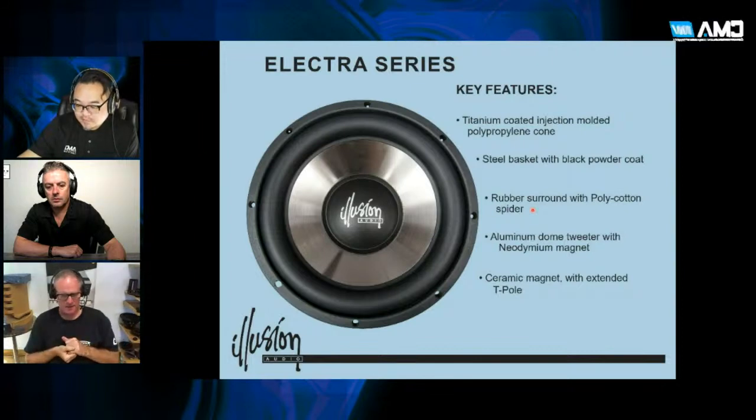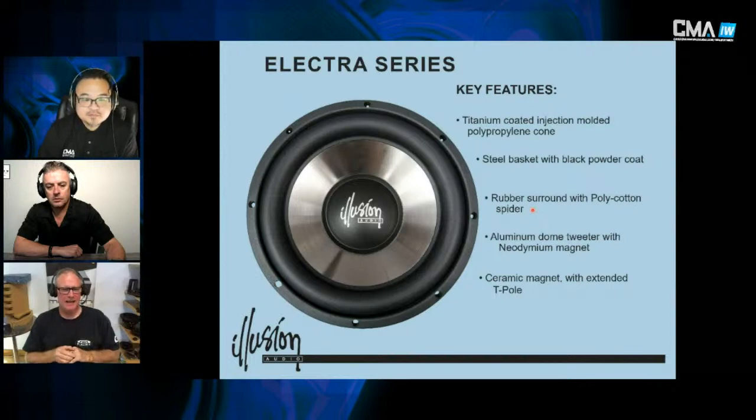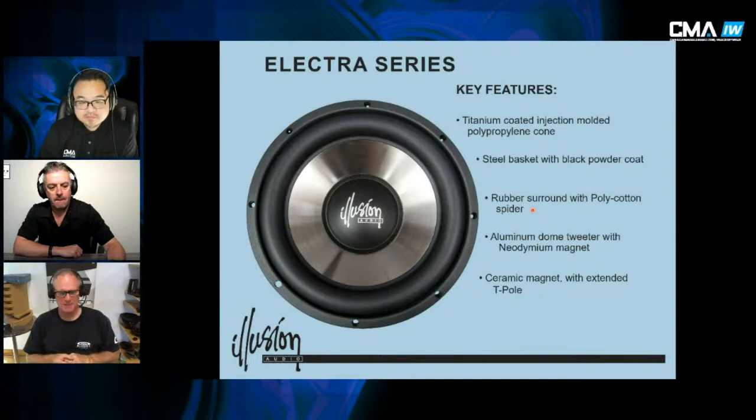A typical cotton spider, if I was to run it to suspension maximum, which is louder than you should be playing it, it will last in that power test 12 hours, best case. The polycotton will easily go 7 days. And Conex, I've run the things over 30 days, 24 hours a day, 24/7, at suspension max. Stop the test, no damage, still within Thiele-Small parameters. So Conex is a major, major improvement.